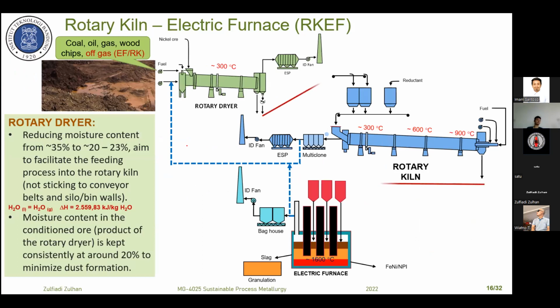Now we look one by one. We have also discussed before. The rotary dryer. The function of the rotary dryer is actually to remove the water content or moisture from around 35% to 20 to 23%, with the aim of facilitating the feeding process into the rotary kiln.